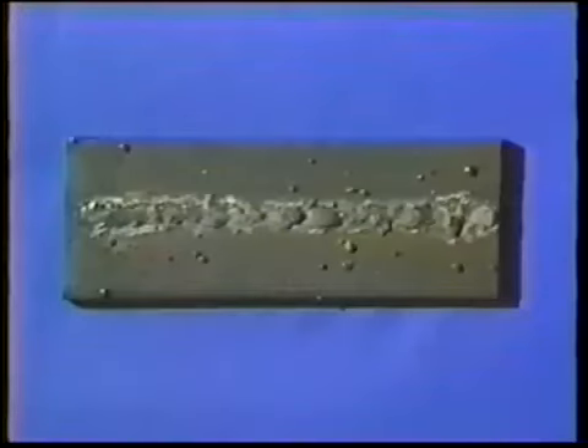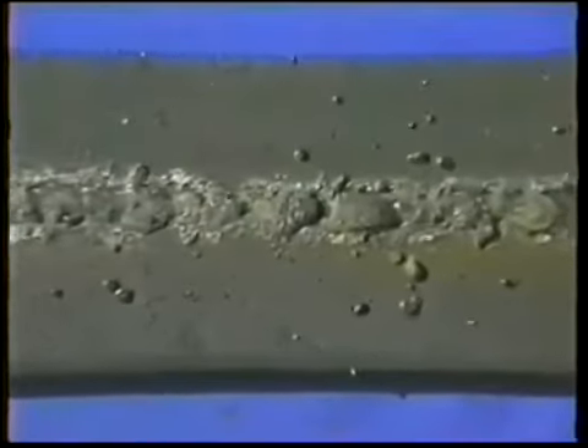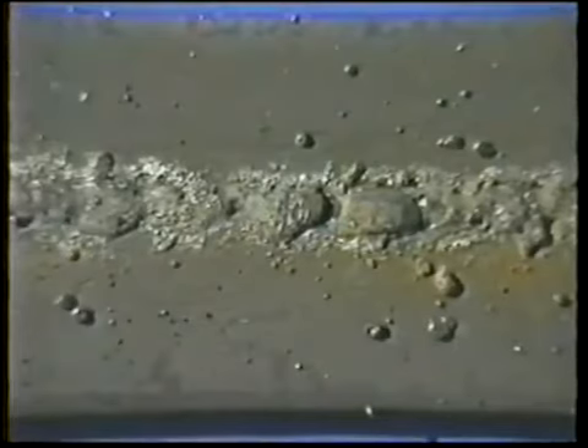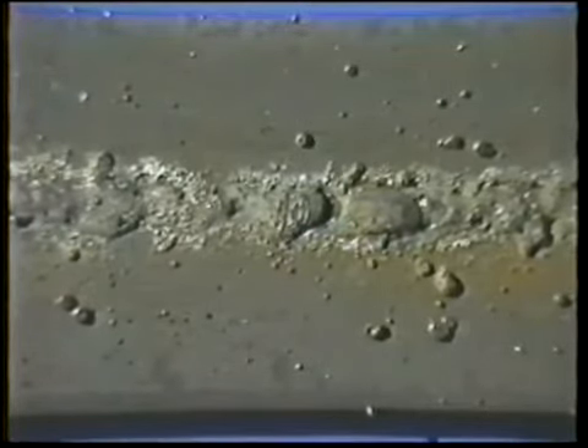If the arc is too long, the metal melts off the end of the electrode in large globules. These globules wobble from side to side and drop onto the work in the form of spatter rather than as useful weld metal. A wide, irregular bead results with excessive spatter and undercut. The weld metal is deposited on top of the plate with poor fusion between the base metal and the weld. Slag inclusions will probably occur.